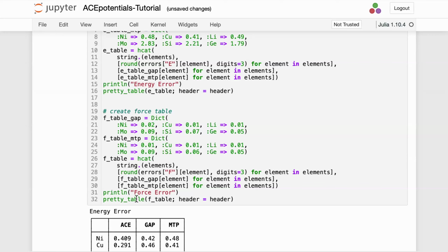So in your training data, if I subtracted the energy of some other model, then it would... You could, if you did that in a pre-processing step, then you could think of it as a correction. I think it sounds like a great idea to try. I think what people have found who did try that is that it makes the problem harder, not easier. Because when you subtract an empirical potential from DFT data, the correction ends up often being harder to learn than the original. That's because the empirical potentials themselves are often easy to learn, and it's the extra stuff that they don't have that is difficult.